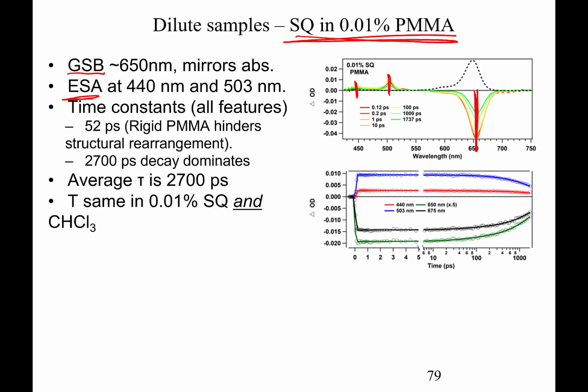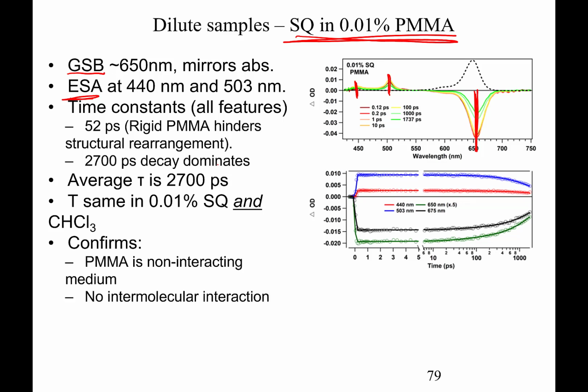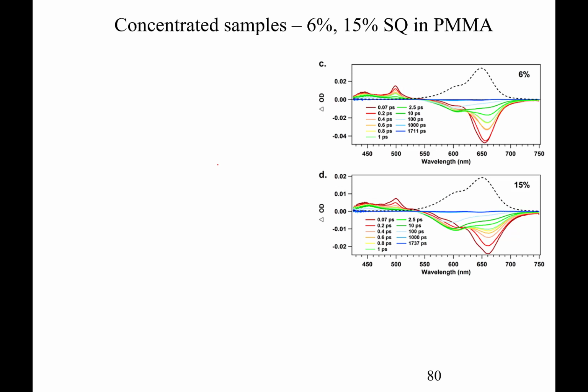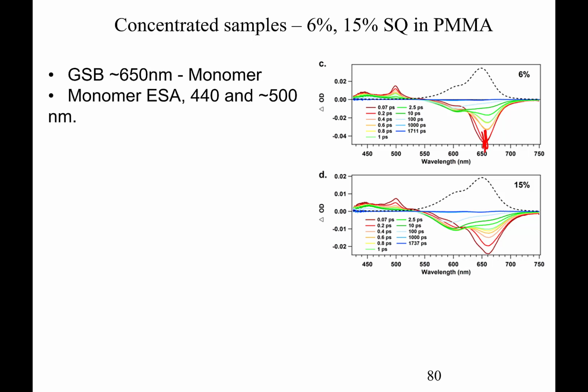So that lifetime tau is the same in the solvent as it is in the low concentration solid solution. So it basically tells us that the polymer is a non-interacting medium. There's no intermolecular interaction between the squaraines. So what happens as we start to increase the concentration of these squaraines in that polymethyl methacrylate film? Well, here's what happens. So the ground state bleach for the monomer still shows up here at around 650 nanometers. We also still see a monomer excited state absorption at 440 nanometers and at around 500 nanometers.